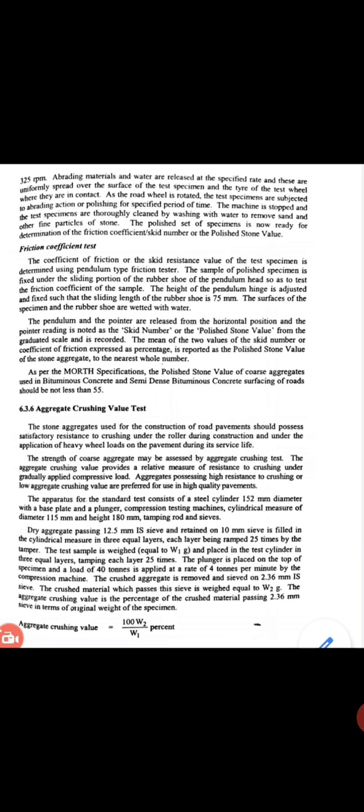Abrading material and water are released at the specified rate and uniformly spread over the surface of the test specimen and the tire of the test wheel as they come into contact. As the road wheel is rotated, the test specimens are subjected to an abrading action or polishing for a specified period of time. The machine is then stopped and the test specimens are thoroughly cleaned by washing with water to remove sand and other fine particles of stone. The polished set of specimens is now ready for determination of the friction coefficient and Polished Stone Values.